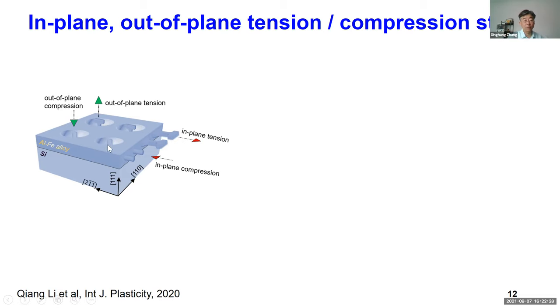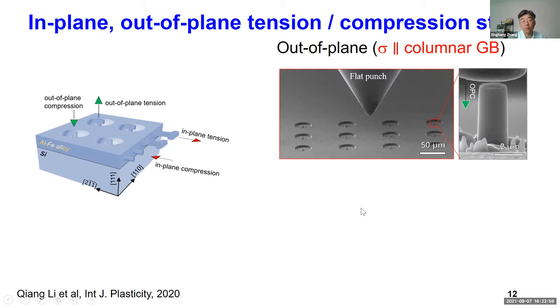So this cartoon shows the test we did. Basically you can FIB out the pillars and the tensile dog bone specimen. And this is relatively thick film, about 20 micron. Now if you do this testing, you can do it along the out-of-plane direction, out-of-plane tension or compression. You can also pull in plane, within the thin film planes, in-plane tension or in-plane compression. That's the setup we did.